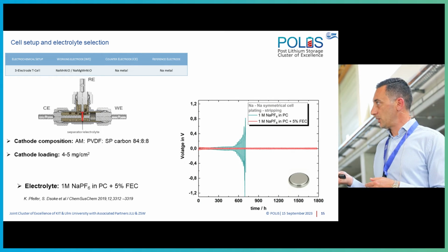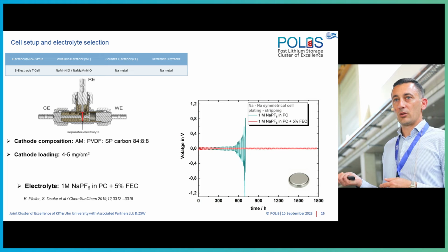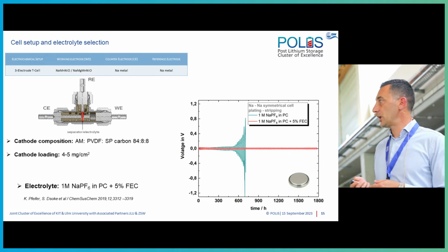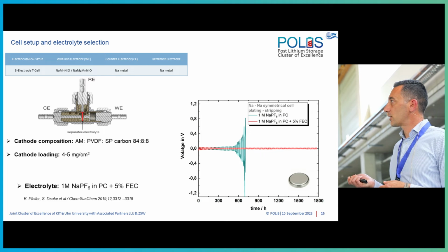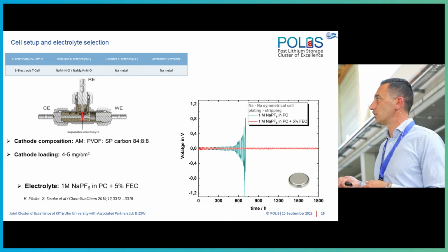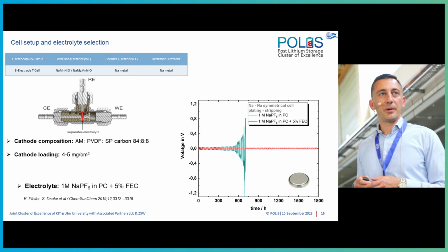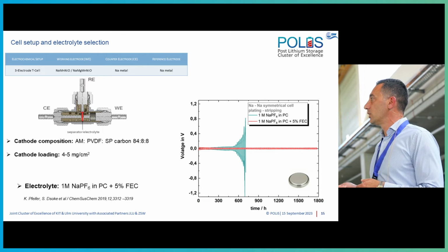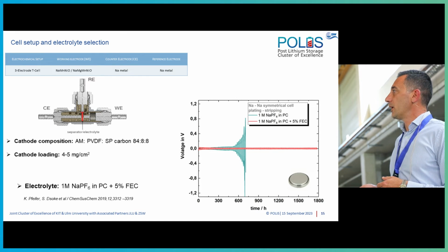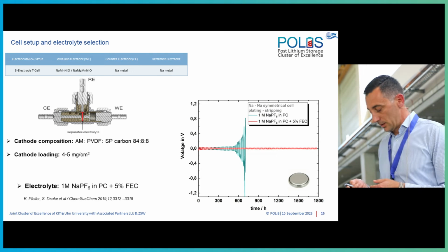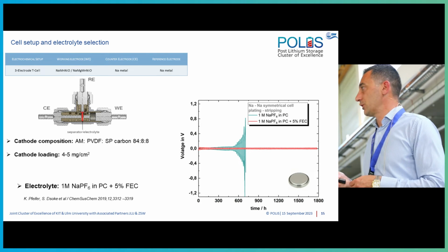Now, if you look, basically, this is only sodium metal stripping and plating. You can see that basically the FEC-free electrolyte, after 600 hours, it just gives up. Yeah? So this is a clear sign of a short circuit. And what we have here is a much more stable cycling behavior.